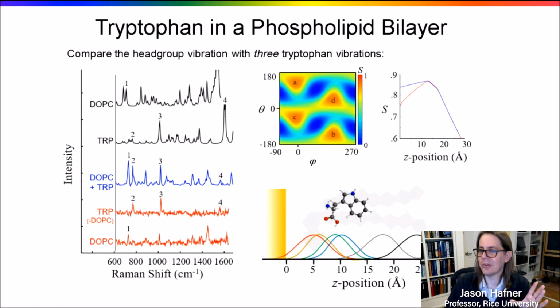As we do our analysis, we get high similarity at 4 places, but 2 of them have it going the wrong way, so we know those are wrong. The other 2 are mirror images of each other, so we only got one answer. The answer is that the long axis of the ring is oriented 53 degrees from the normal, which can be measured one other way: with polarization or polarized fluorescence, you can get this direction. So we got basically the right answer, 53 degrees.